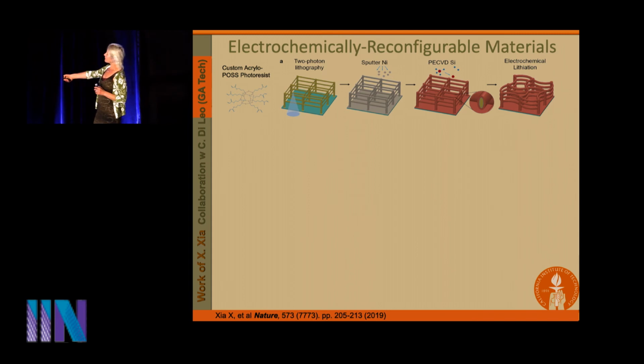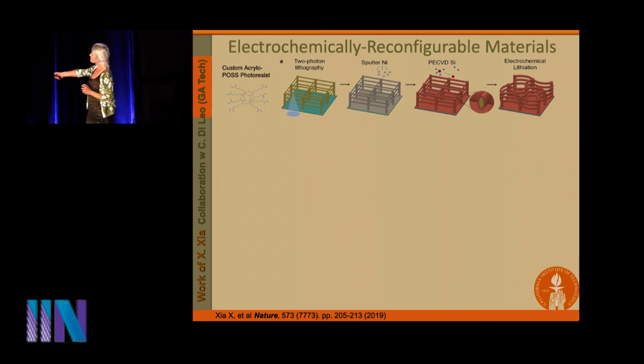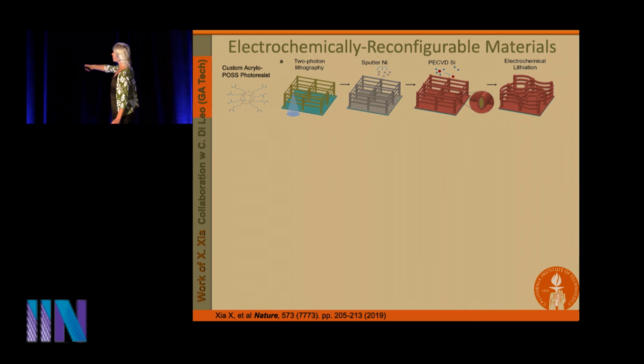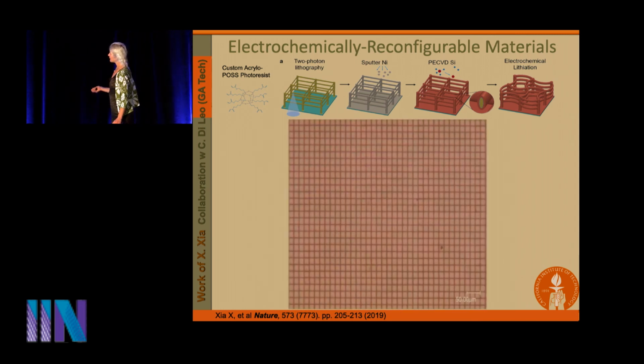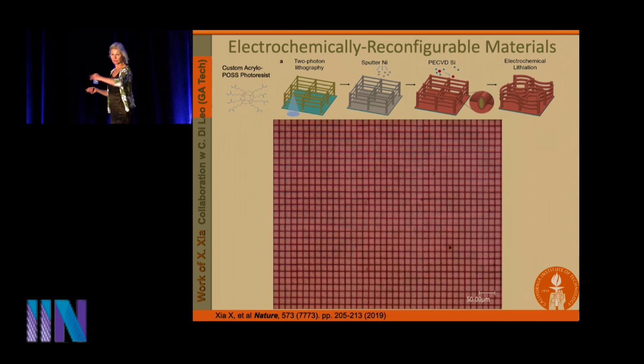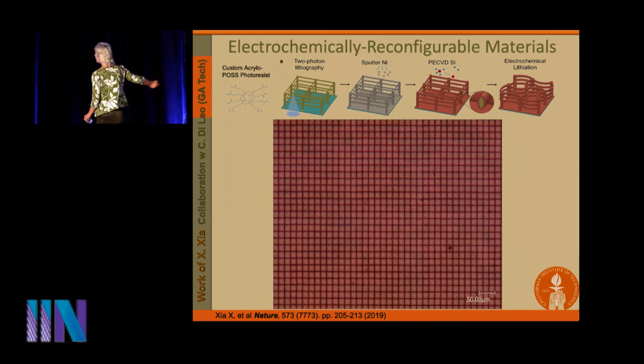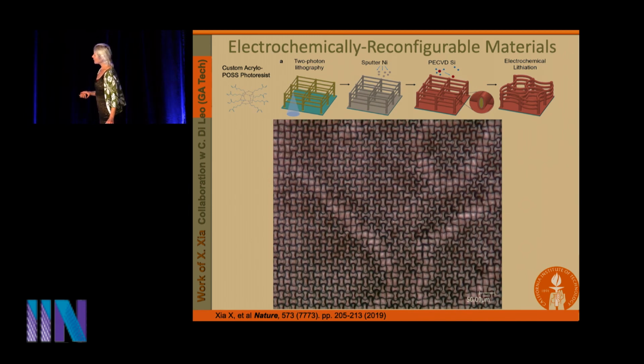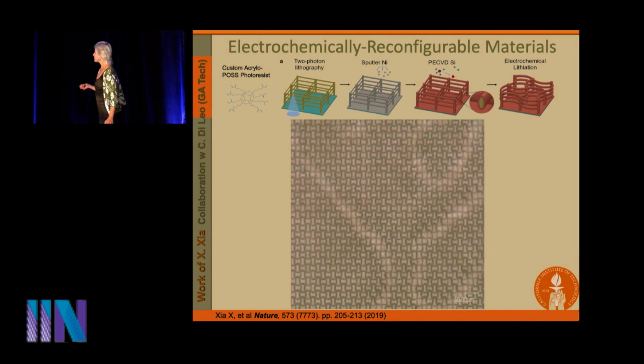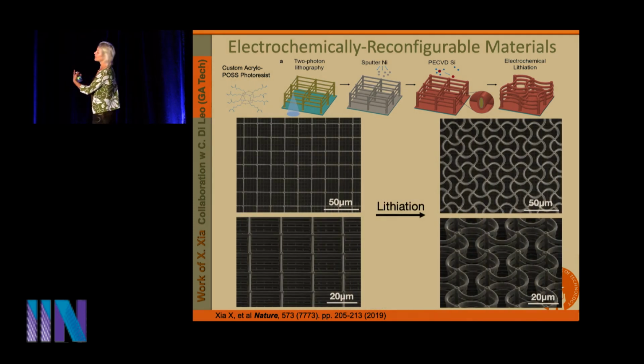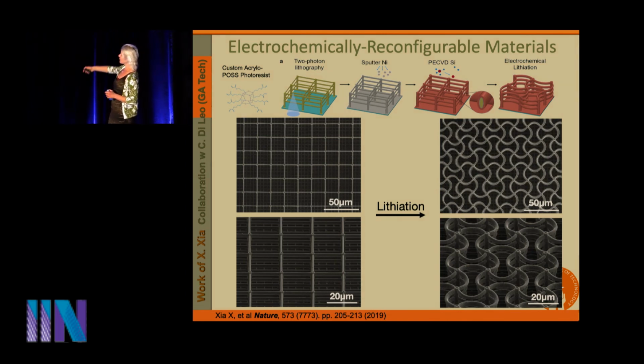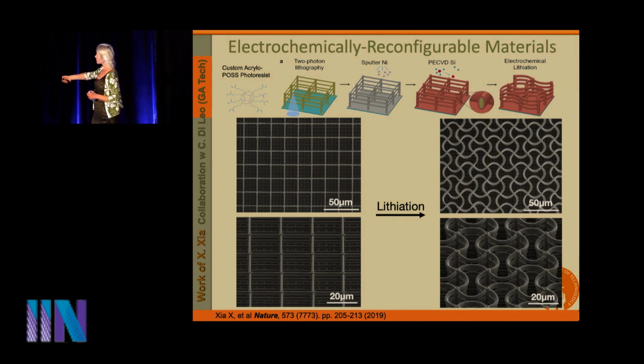So this is a tetragonal microarchitecture. And you can see that there are beams basically subtended over these unit cells of tetragonally shaped lattice. And the idea being is that once you lithiate it, they will buckle out of plane. And so here's one of these. This is a top view of one of these lattices as they're being lithiated. And you can see what ends up happening is that these are these sinusoidal type patterns that evolve. Actually, they look like violin. I'm a musician, so to me they look like violins. So you can see these sinusoidal patterns that are developing in response to lithiation.